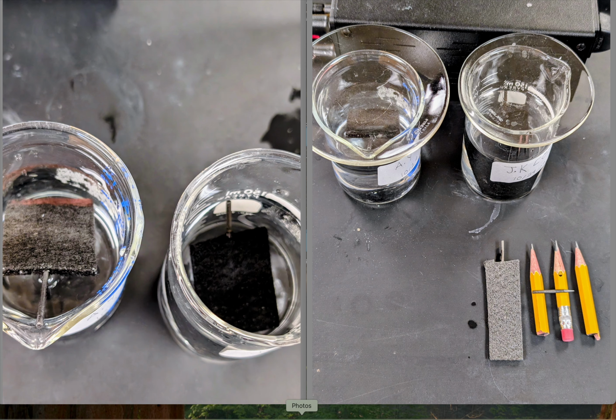And at the end of 45 minutes, we stopped. And the voltage had gone up to 5.9 to 6.0 volts because the resistance is increasing with constant current. The graphite felt becomes less conductive. We're disrupting the pi system. But we will find, we hope, the polypyrrole polymer will deposit and be anchored more in place with the oxidized moieties on the graphite felt.